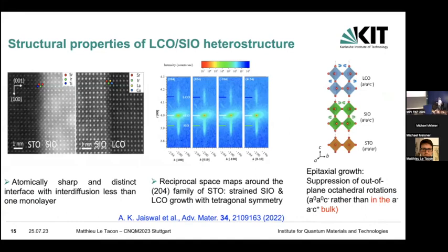So we actually grew a series of layers using lanthanum cobaltate in contact with strontium iridate. We see we have an atomically sharp interface, that's an electron microscope picture, with no interdiffusion either from the titanate to the iridate or from the iridate to the cobaltate. We can fully strain them. These are reciprocal space maps that show you that